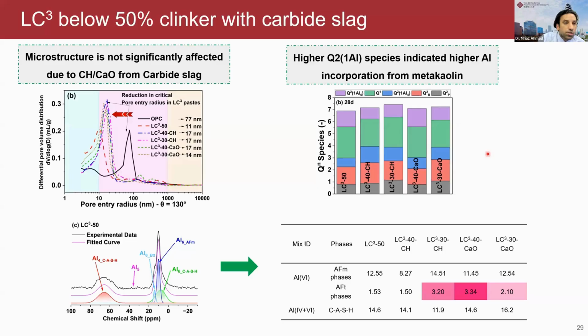And further, we looked into the material's microstructure, and we observed that carbide slag actually does not damage the microstructure. It has a very similar microstructure as compared to LC cube 50 and much superior as compared to the normal cement. You can see here these are the results from NMR, and we observed that the calcium silicate hydrate binding gel is in almost similar quantity or even slightly higher quantity than LC cube 50. And most of this aluminum was also found in other phases such as ettringite and AFm phases.